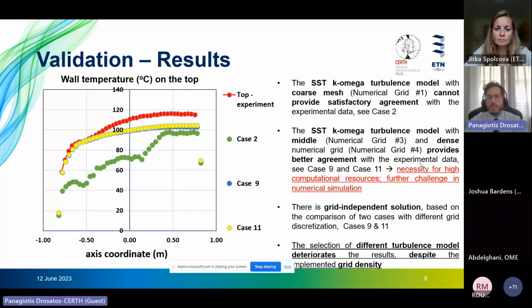Based on the simulation we performed, we derived this spatial distribution on the top of the heated horizontal pipe. As you can see, the SST k-omega turbulence model with coarse numerical grid is incapable of providing satisfactory agreement against the experimental data. See case 2. On the contrary, when the same turbulence model is utilized with middle or very fine numerical grid densities, then there is a better agreement with the experimental data. The necessity for high grid densities implies further challenges in the numerical simulation.